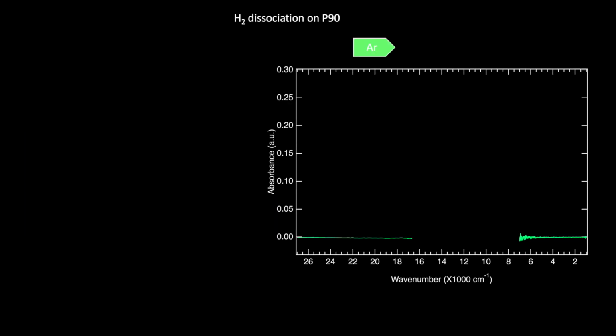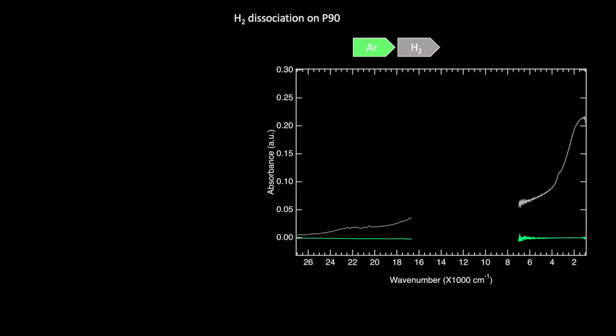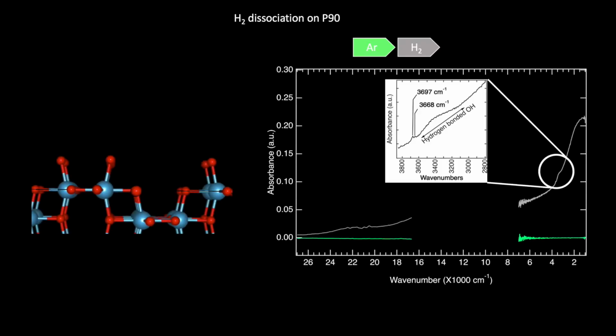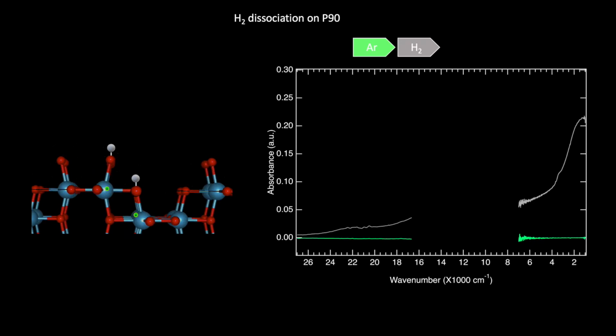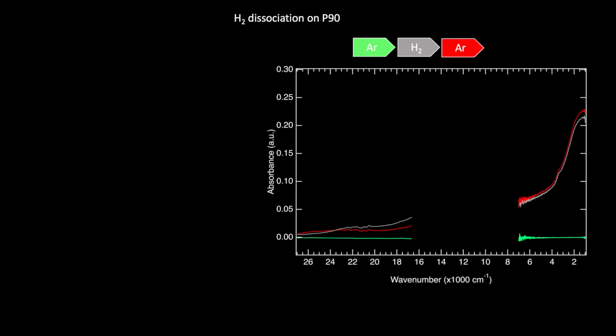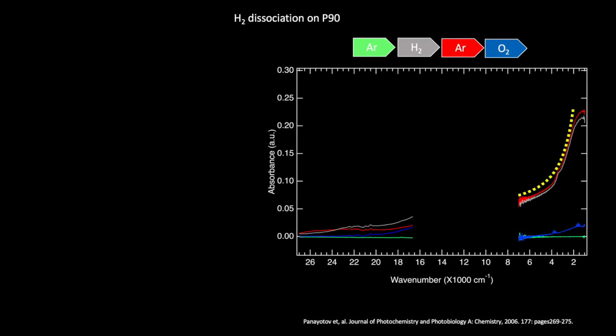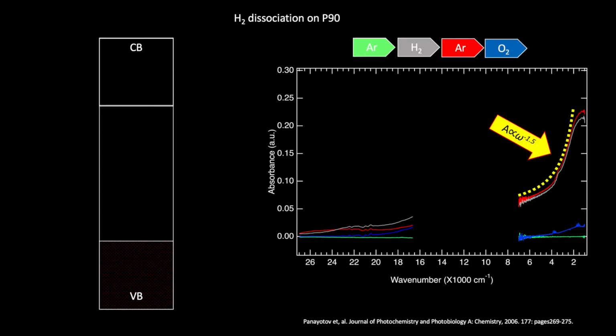After switching the gas flow from argon and exposing the P90 surface to hydrogen, surface hydroxyl groups reappeared as the sign of production of electrons. At the same time, a broad background absorbance developed under hydrogen and it was stable under argon flow. The broad background absorbance disappeared quickly under oxygen flow. The shape of the background absorbance, which increases toward lower wave numbers as a power function, is a sign for presence of electrons in the conduction band. The absence of any significant absorbance in the UV visible region of the spectra shows that there are no unoccupied electronic states available for electrons in the P90's band gap.